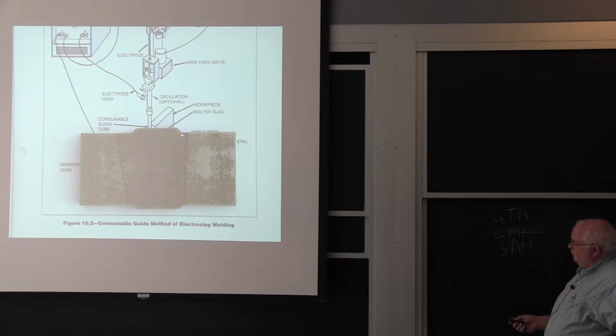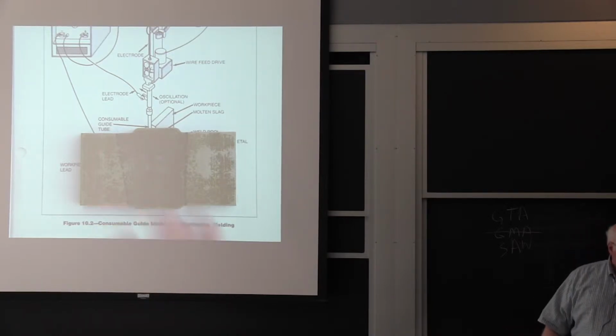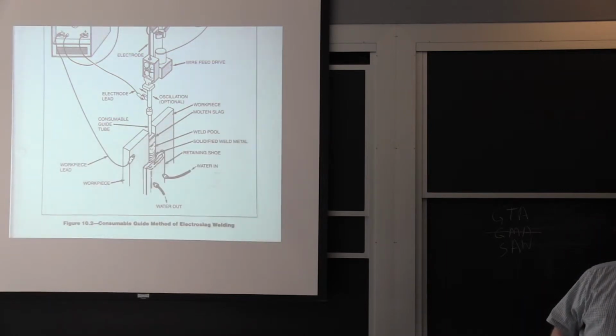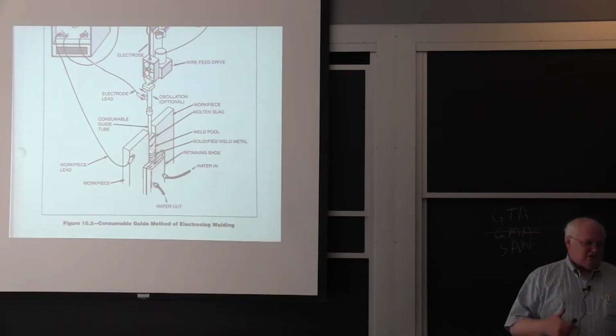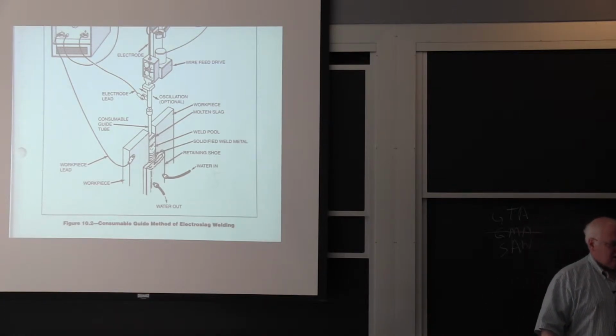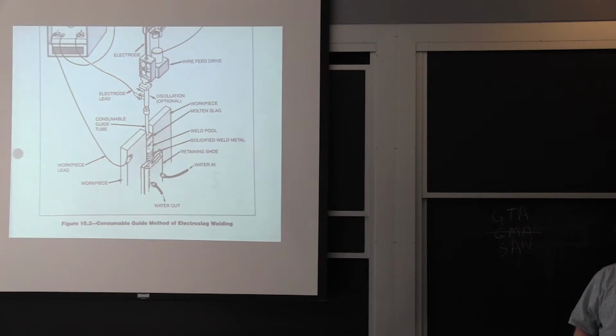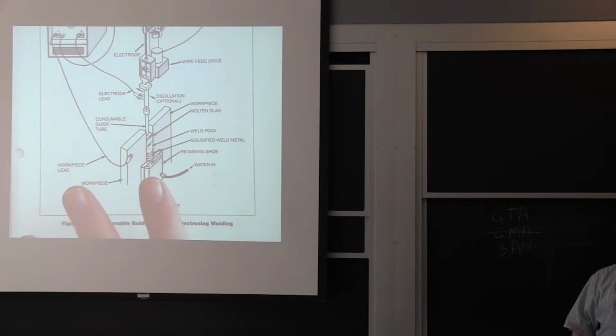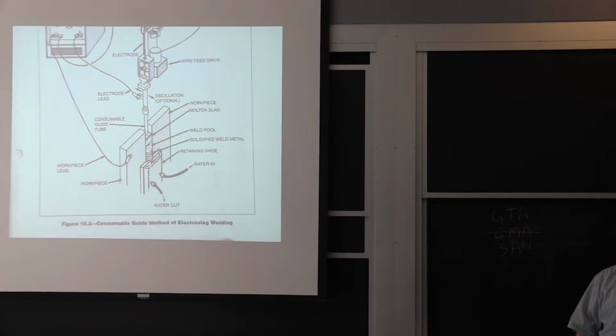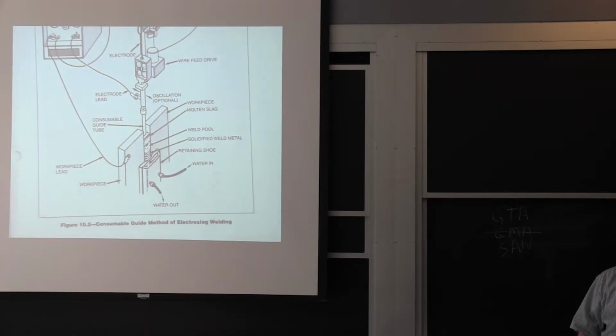These are the reinforcements from the water-cooled copper dam, so on either side. And here's, I've outlined, this thing was painted, or I put crystal clear on it, and it's been wearing away over the last 25 years. But this is an Electro Slag weld on 2-inch thick titanium. And titanium doesn't have some of the problems that steel has with bad grain size and poor toughness. And so you can bet that this is one of the technologies the Soviets used to weld a lot of their titanium hull, was Electro Slag. And I won't say any more than that.